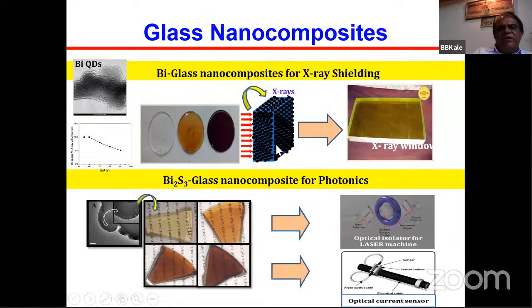This is bismuth sulfide quantum dots glass, and we observed that this glass can be used as an X-ray absorber. Instead of lead, we can use very small nanoparticles of this compound inside the glass, which can absorb X-rays. It's a transparent glass. Inside the transparent glass, these are the nanoparticles we can see.